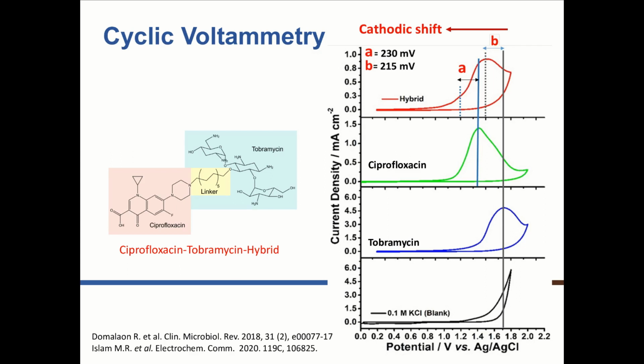Here on the right-hand side, you see examples of these voltammograms for different antibiotic species. In blue, you see the electrochemical signature of tobramycin, a very common antibiotic, in green, ciprofloxacin, and in red, we see an antibiotic hybrid. You can see that these reactions are not chemically reversible because we don't see a reduction peak, but we do see a pronounced oxidation peak for both tobramycin and ciprofloxacin. When we investigate hybrid molecules that are designed to trick cells into consuming a certain antibiotic they might be resistant to, we see in the red curve a pronounced oxidation peak that corresponds to tobramycin, but also a small shoulder peak that is attributed to ciprofloxacin.